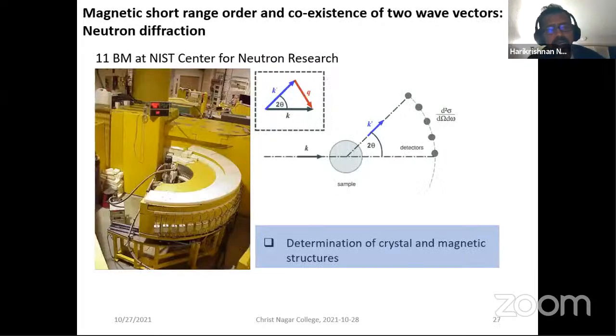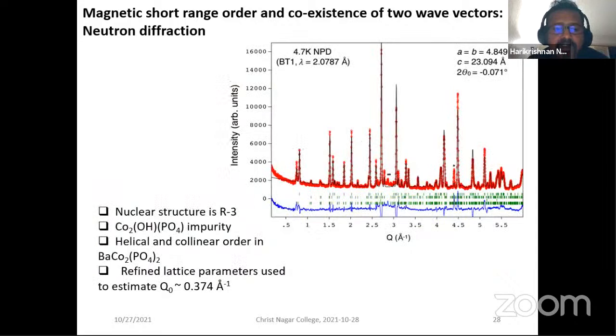Now comes the main part. We want to study it using neutron scattering. We do that to understand how the magnetic entities, the spins, behave. There are two types: elastic scattering and inelastic scattering. The first one is done to find out the magnetic structure, the static magnetic structure. And the second one is done to find out what the excitations are. So the first one would tell you what the ground state looks like, and the second one would tell you what excitations are there. When we do the diffraction, we find that it actually has two types of ordering instead of a single ordering.